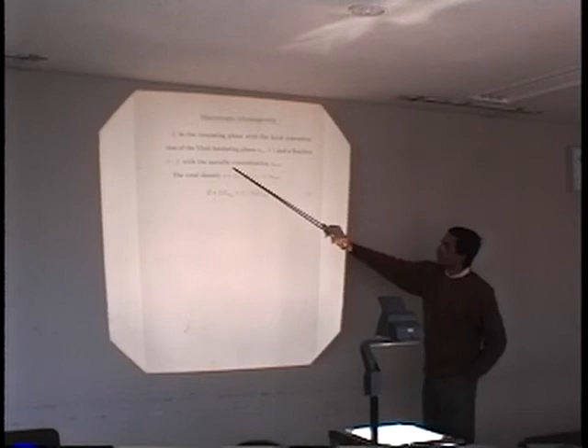What you then say is that you try for an electron density of n, let us say, in the case of lanthanum strontium titanate, for example. Suppose it phase separated into f amount of lanthanum titanate and 1 minus f amount of strontium titanate. Then, of course, it has to be satisfied that the total number of electrons doped is equal to the portion that has become lanthanum titanate multiplied by 1, which is the number of electrons in the insulating state. Lanthanum titanate has 1 d electron. And this is the portion that is the metallic state, 1 minus f, and the concentration of slightly doped.